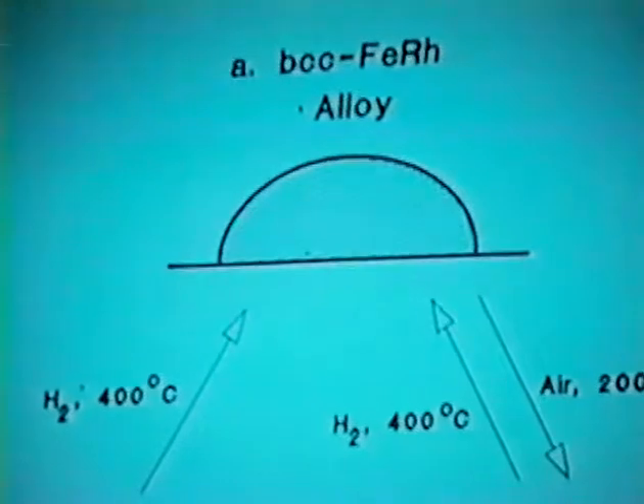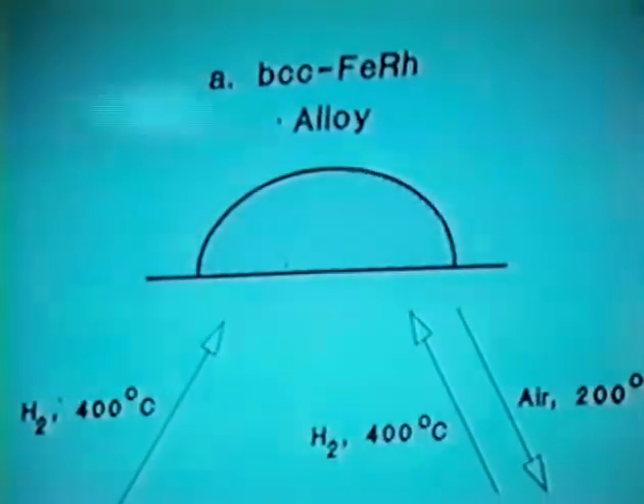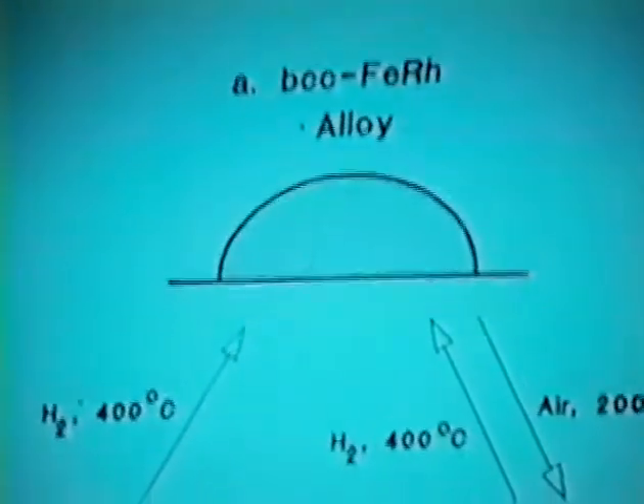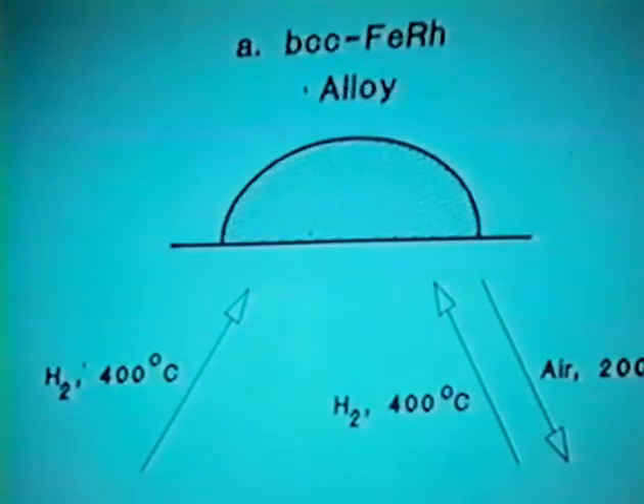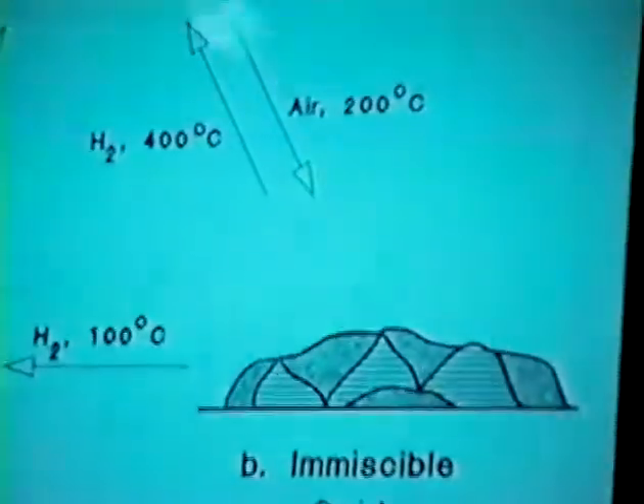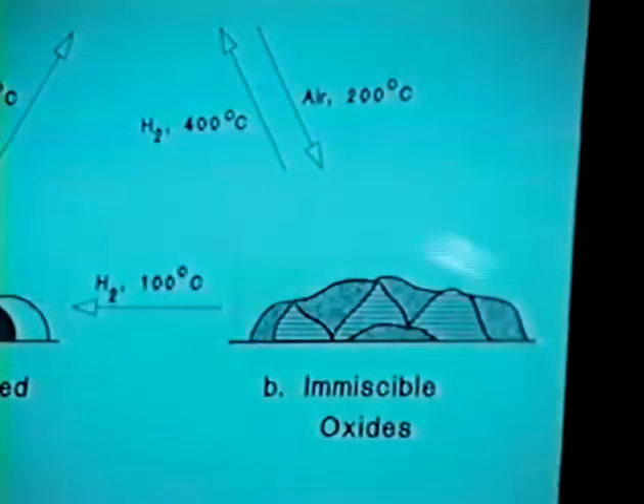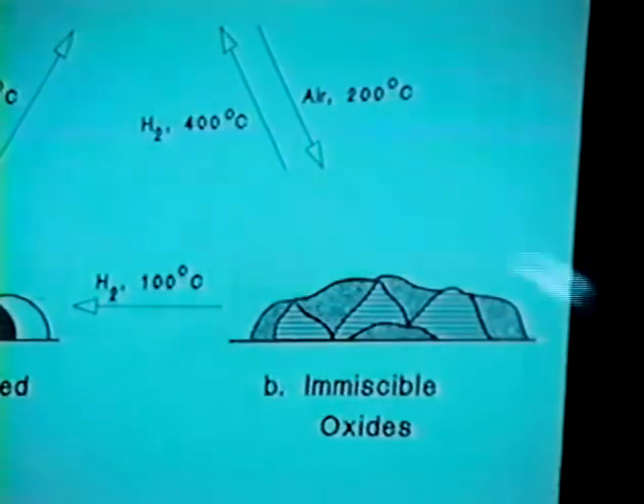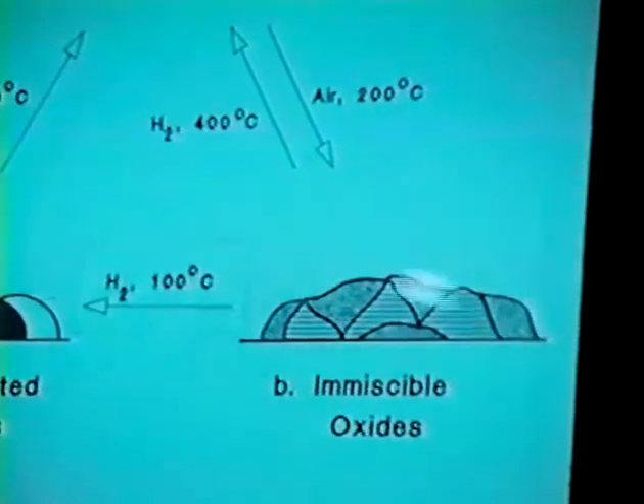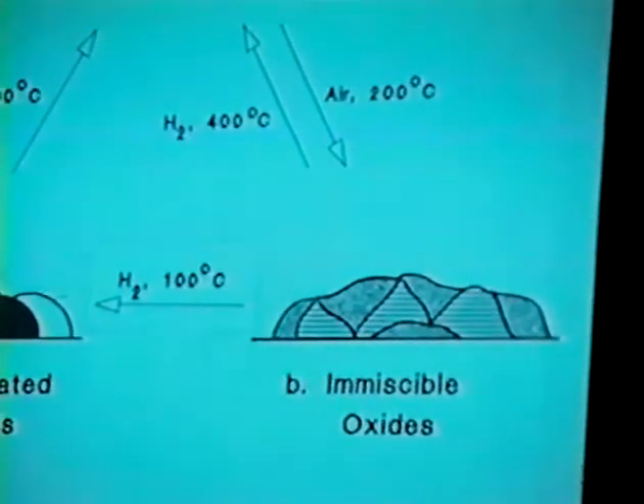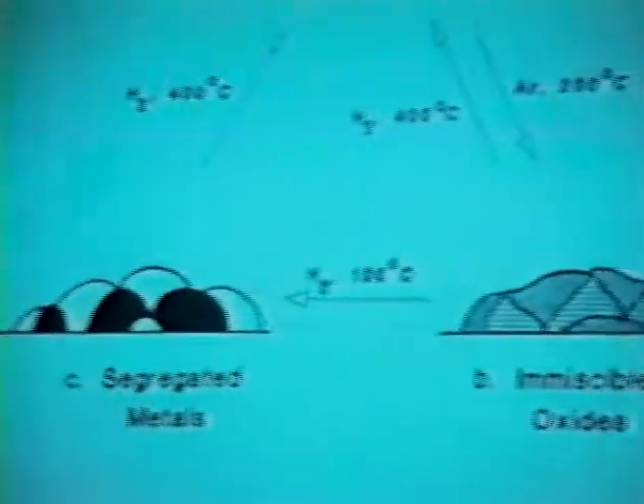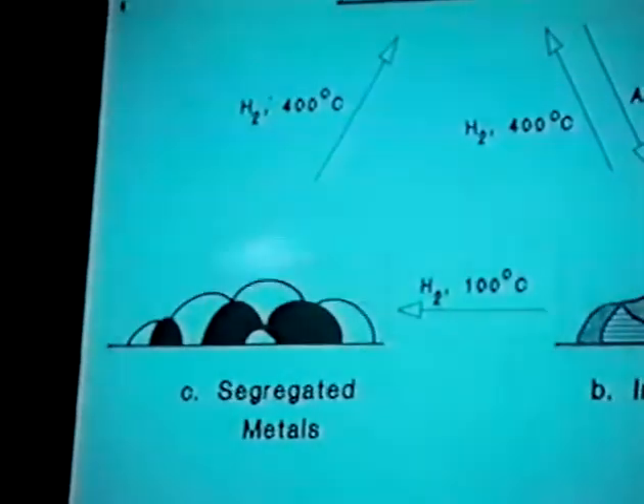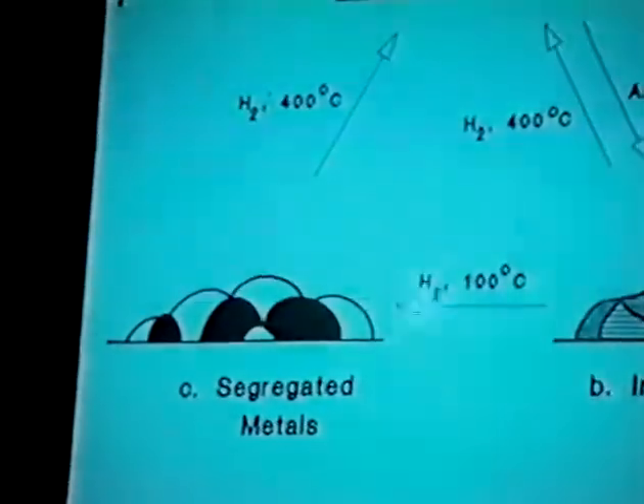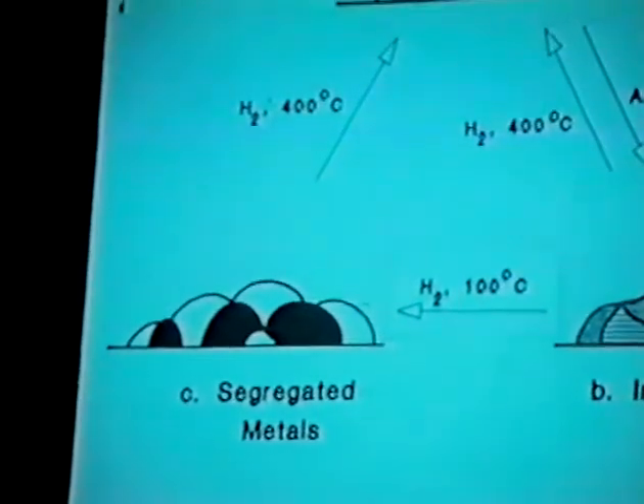we're looking at. After the high temperature reduction step, we've got these nice uniform crystallites of BCC bimetallic iron rhodium alloy. After the high temperature, 200 degree or above, oxidation, these particles tend to segregate into smaller zones of iron oxide and rhodium oxide, which still exist inside the same larger particle, but the surface tends to be enriched in iron. I'm basing that on the heat data that we got on adsorption of oxygen onto this structure, which tended to show that we had a surface that consisted primarily of iron.